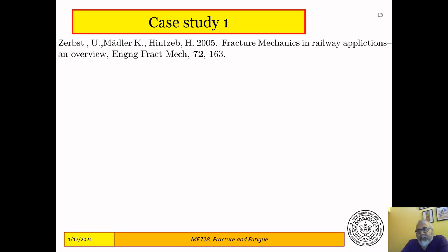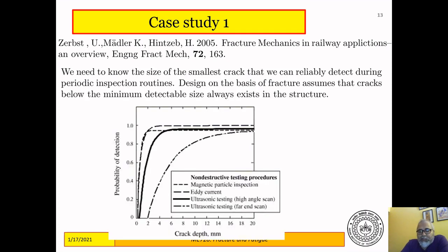For example, in this railway application example, these are some of the processes. You don't need to really worry about what these processes actually do. These are some of the processes by which you detect cracks in a structure. So you have these railway wheel axle assemblies, and there you use one of these methods to detect whether it has a crack or not. And each of these methods will have a resolution. That means there would be a smallest size of the defect that it can reliably detect. For example, if you take ultrasonic testing, then the probability of detection is almost 1 once the crack size reaches a depth of about 6 millimeters.